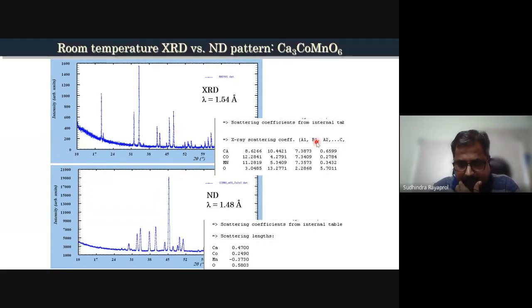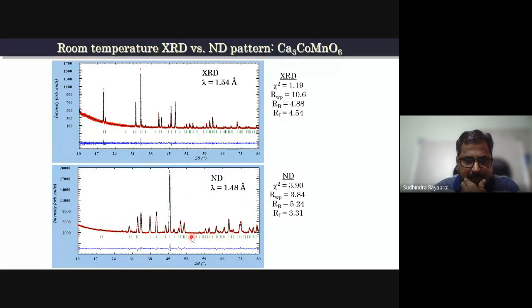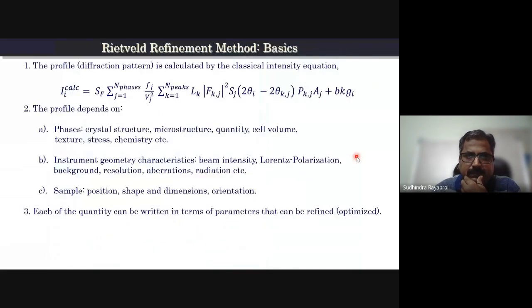Okay. So this is the main reason why you see that certain peaks have better intensities in case of X-rays and neutrons have better intensities for certain peaks. And using the same structural model, I can refine both X-rays as well as neutron data with very good refinement parameters in both the cases.